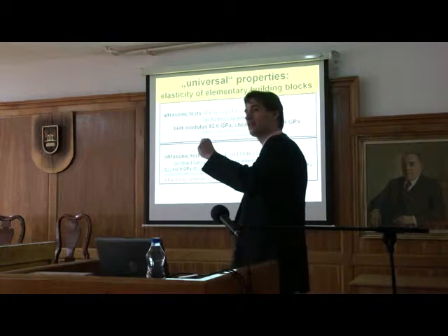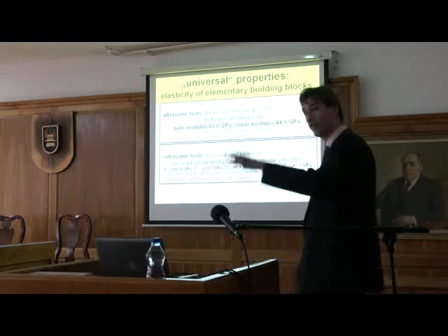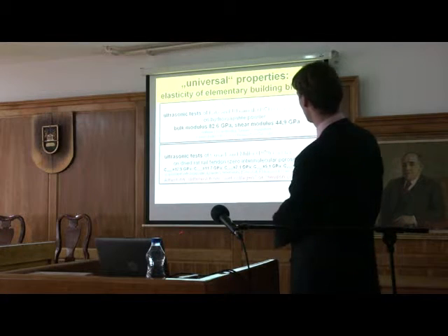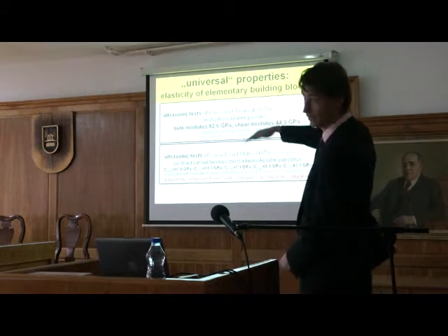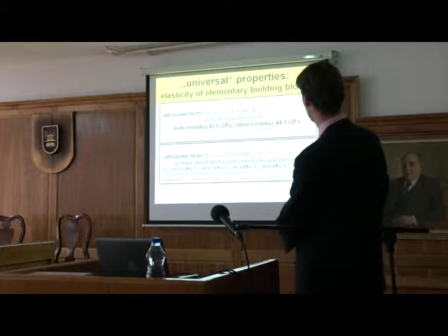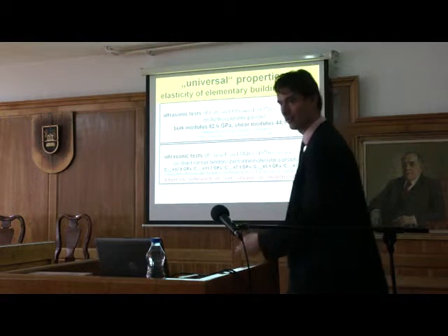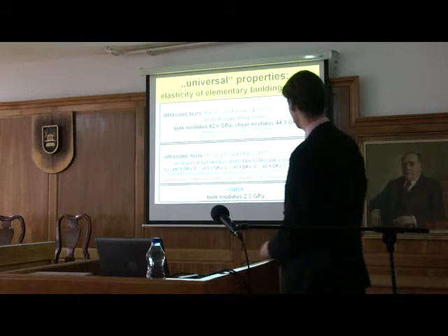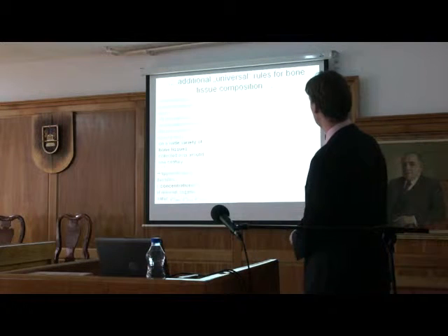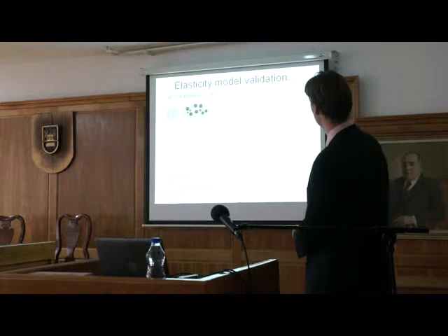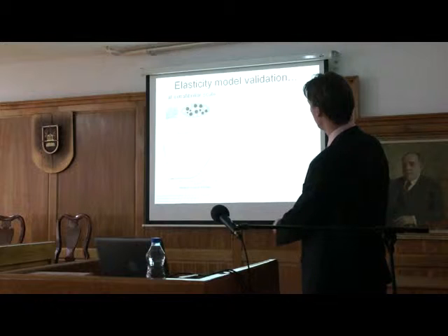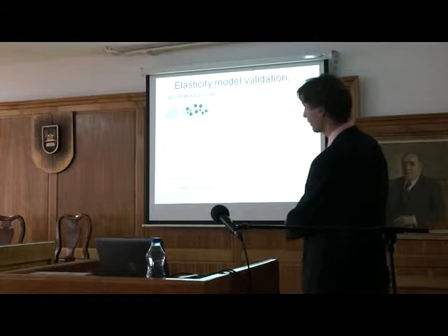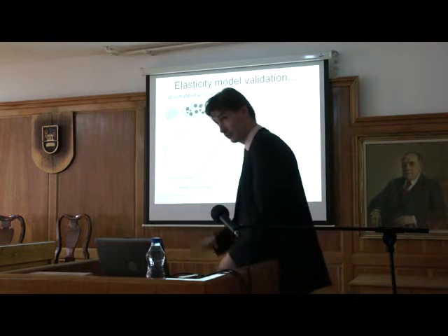What you have in the literature is very often a composite between collagen and water, or a lot of water, and then it goes down orders of magnitude. But this would be a higher step of the model, so attention. I'm not talking about wet collagen. It's collagen. Okay, and water. And these are these rules from before, and if you put it there, at this scale, almost a perfect prediction. There's no fitting, zero fitting.